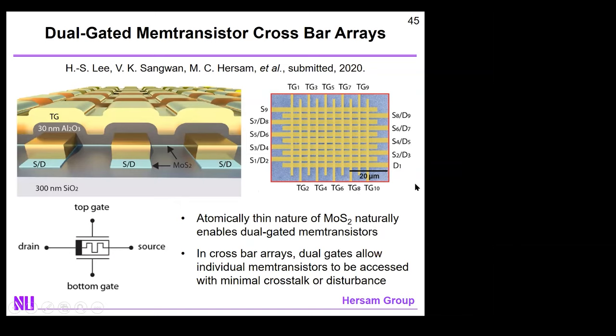Of course, if we went to a proper clean room like at a company, we could push this down a lot farther. I don't think it's really a lithographic question. The question, as I alluded to before, is if you scale the memtransistor channel, does the device still work? And that, in the current design, requires going to smaller grain size. In fact, there are other groups that have since shown that as you scale the grain size, you reduce the dimensions of the device and therefore the operating voltage. But as I mentioned before, I don't think that's the end game strategy, because at some point the material becomes amorphous if the grain size becomes too small, and I'm not convinced it'll work in that limit. And so what you'd instead want is a means of intentionally introducing the defects